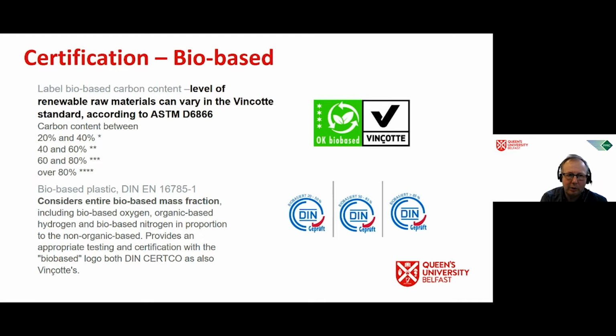The DIN standard is for bio-based plastics, and this DIN standard considers the entire bio-based fraction, including bio-based oxygen, nitrogen, and hydrogen, compared to the non-organic fraction. And this provides for certification, and provides a DIN stamp for how much bio-based material is in there, between 20 to 50, 50 to 85, and then greater than 85. But it also has a bio-based logo, which can be used with this certification.